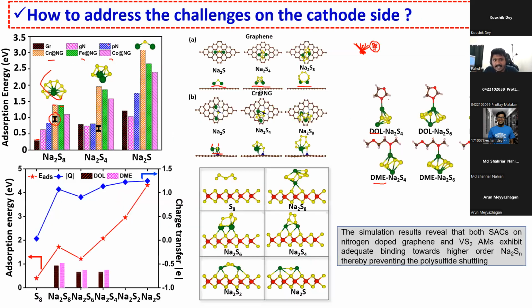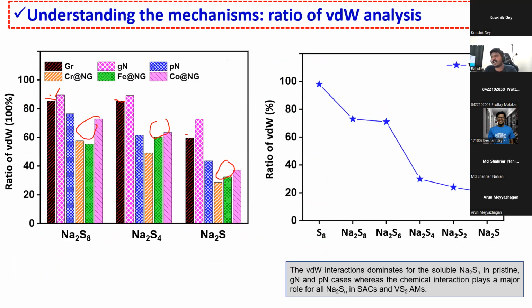That's the reason why you can see here that Na2S binding is very much higher when compared to Na2S4 and Na2S8. Na2S binding energy is around 3 eV. That's the reason why the chemical interaction is higher. That's the reason for the higher binding energy. And this is for the VS2 substrate.